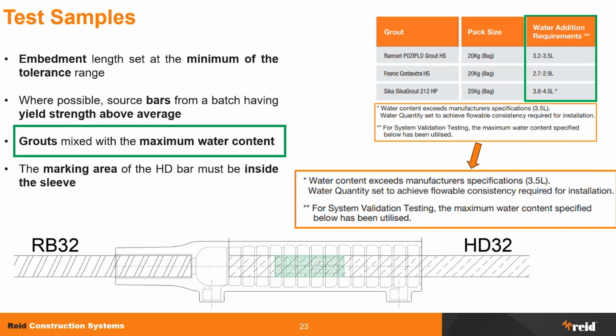This came with feedback that we had, again, from the testing laboratory. Because what we asked for is not just to test for the strength of the grout, but also to test for the flowability. We wanted to ensure that it was easy to install and to grout. The feedback was that when the grout, in this case Sika 212 HP, was mixed with 3.5 liters, it wasn't as flowable as the other two grouts. Therefore, the consideration was, if that happens on site, people might add more water. And so we agreed to increase the water content to 4 liters and test it that way. And the test was successful. So that's why you will find here that you have a higher water content.